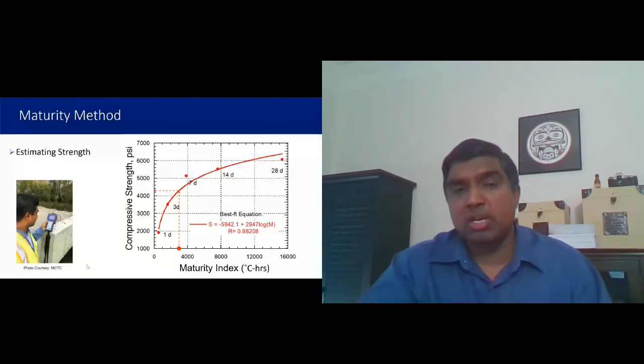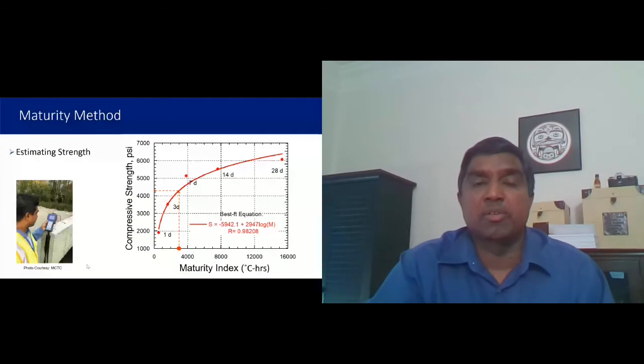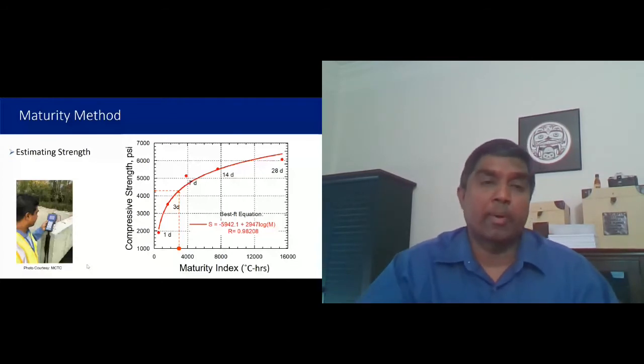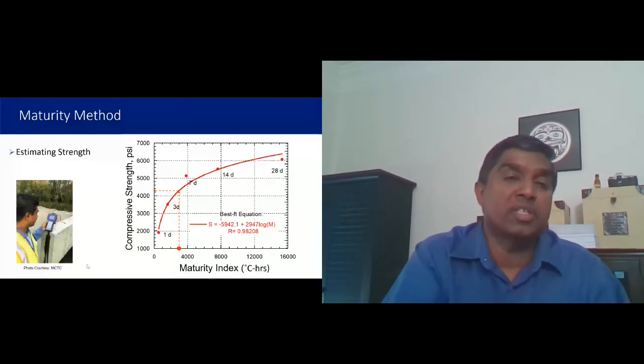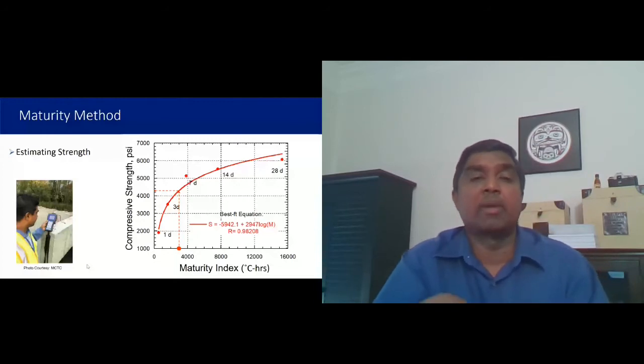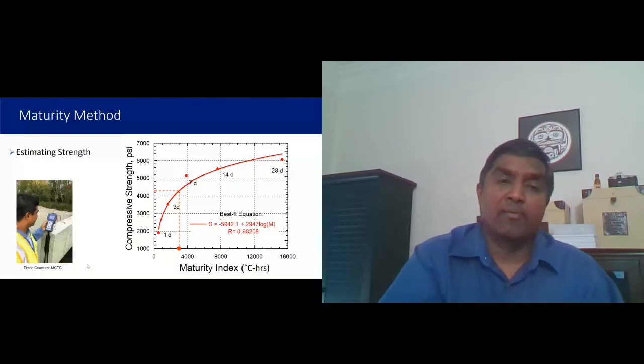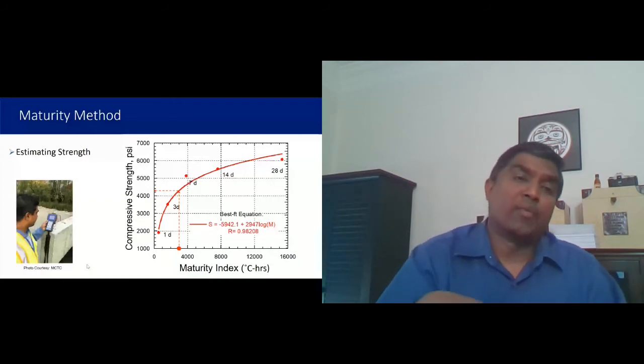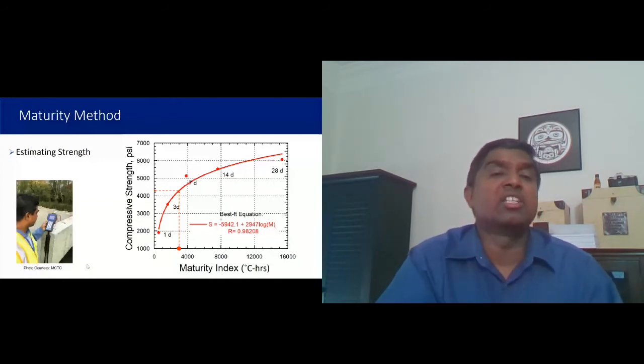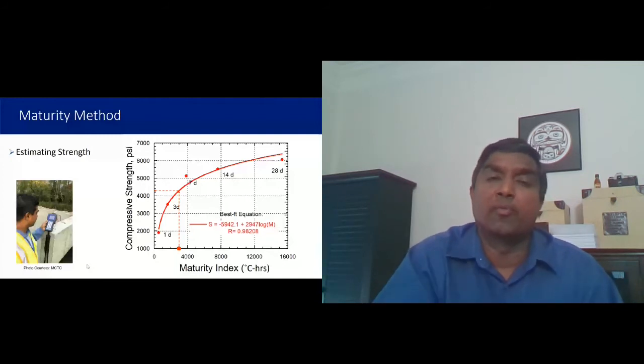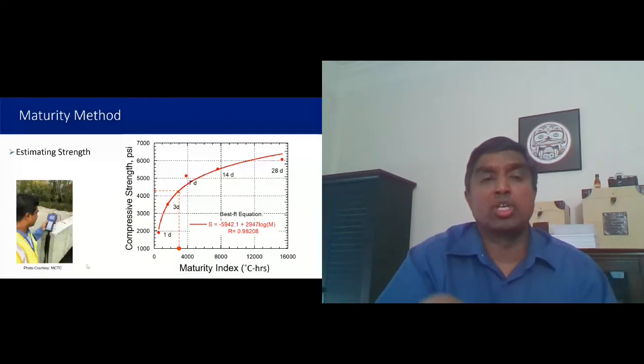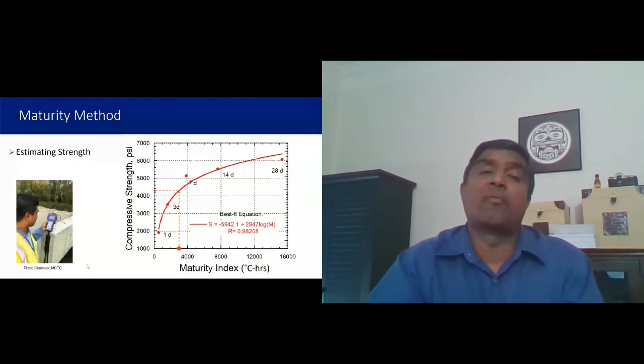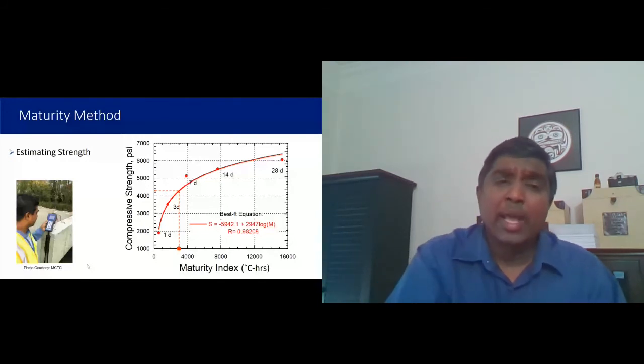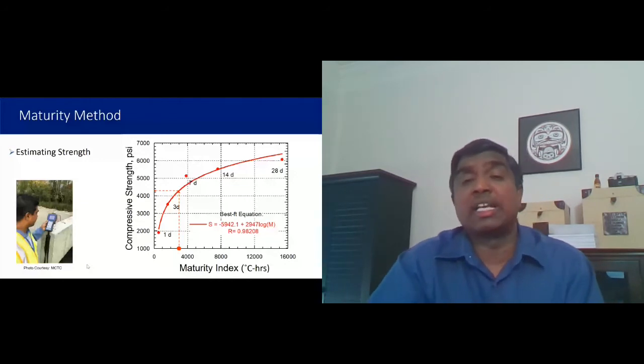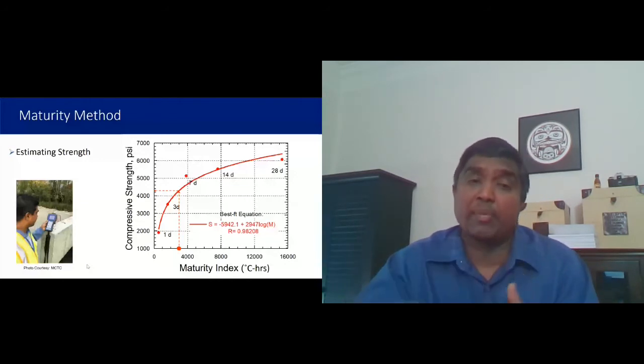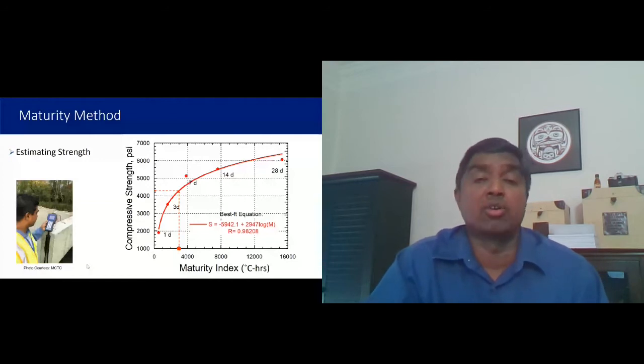So just to summarize or recap the whole concept of maturity. Maturity is a two-step process. In the first step, we cast a bunch of cylinders, and then we break them at different ages. I've listed 1 to 14 days here. If you have early age, high early strength mixes, then you probably don't even need up to 14 days. You can even get away with 7 days. So it all really depends on the compressive or flexural strength that we are shooting for. And then what we do is we record the maturity readings each time a test is done, and then we plot the strength and maturity curve.